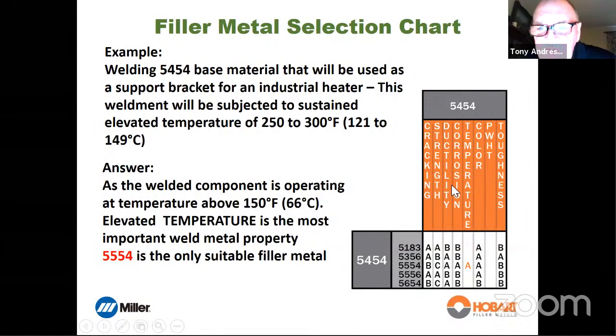Okay, so which filler alloy would we use? It's 5454 to 5454, and it shows we've got 1, 2, 3, 4, 5 different. You could weld it with any of those, right? However, we've got this temperature issue, so we need to look up the temperature. And if we look at the temperature, we'll see there's only one filler alloy we can use. All the others are blank, blank, blank, blank. That means don't use it. Unless it's got a rating, do not use it if that variable is important.